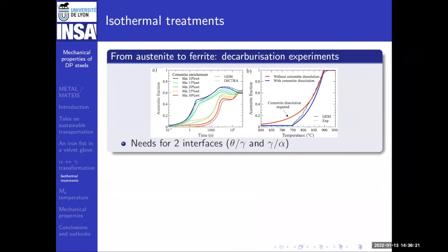Okay, so now that we have this tool, we can study interesting features, like for example, the amount of manganese in the steel, and you can remark that starting from a very low manganese steel, you have a very fast transformation kinetics, and if you increase manganese, there is some kind of threshold here where you end up with a transformation kinetics which is much slower. And for the industrial partner, this was quite interesting because they wanted to know how long, at which temperature, we have this much fraction of transformation. So this kind of graph is interesting for them. Okay?